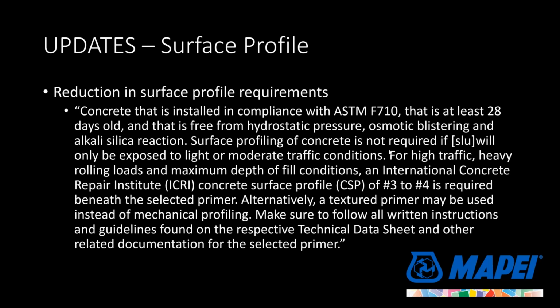When we used to have Portland cement-based self-leveling underlayments, CSP, or the concrete surface profile, was very important, because Portland cement-based leveling compounds grow and shrink a lot more than the calcium aluminate cement-based materials that we currently make our levelers on.